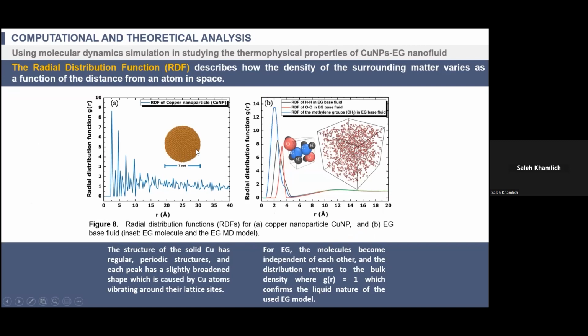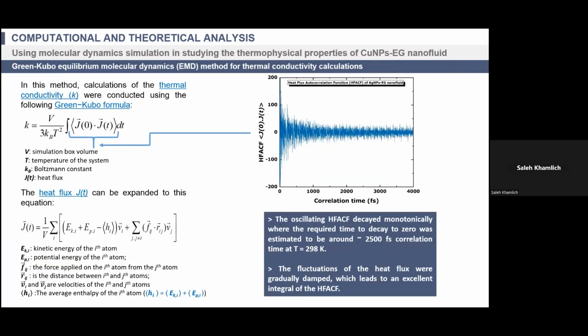call radial distribution function. It shows clearly that the metallic nanoparticle has a regular periodic structure, which proves that it is a solid. For the liquid, we have this kind of configuration, which proves exactly that the base fluid is liquid. Because as I mentioned, we have to simulate like a virtual lab. We have to make a virtual laboratory in order to understand this system.